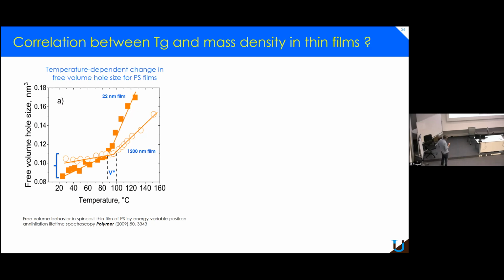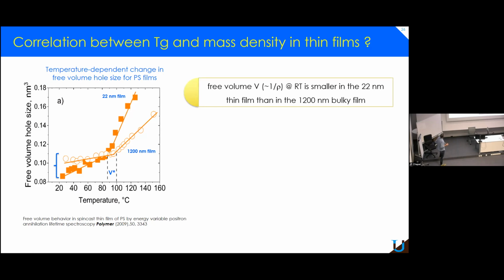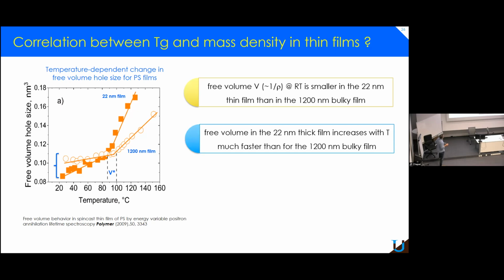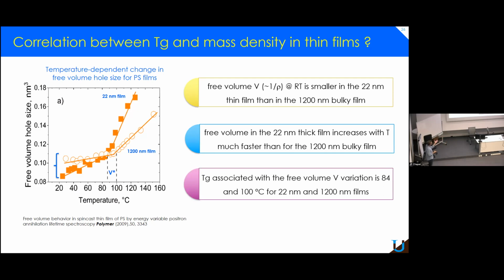So we went into the literature as well, and we found a couple of experiments, but this one is a nice one, where people were measuring the free volume using positron annihilation lifetime spectroscopy, which is typical for that. And what you see here is that, first of all, the free volume at room temperature is smaller in the 22 nanometer film than in the bulk film. You can see there is a big difference. What is more important is that the free volume in the very small film increases with temperature much faster than in the thicker one. You see the slope here? And the glass transition associated with the two thicknesses is 84 degrees for the small one and 100 degrees for the thicker one.